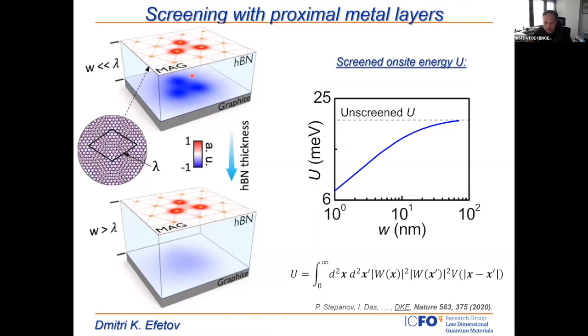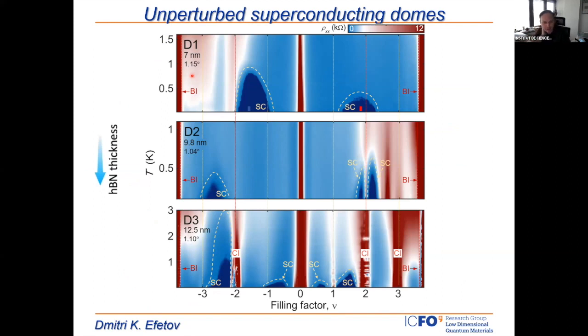And really, in a nutshell, before Gleb did this experiment, we did ours where, in a less controlled way, we just made a bunch of devices with different twist angles and different dielectric thicknesses. And in these experiments we cannot completely distinguish what's more important, the screening or the band structure effect. We cannot completely disentangle it. But what's true is that in devices where twist angle is dead on magic angle and where the dielectric thickness is not that thin yet, we really do see strong correlated insulators. And in the devices where the parameters were shifted, where the kinetic energy is enhanced, and also where the dielectric screening is relatively strong, we don't see correlated insulators. So somehow this proves the point that the correlated insulators can be quenched with these manipulations.